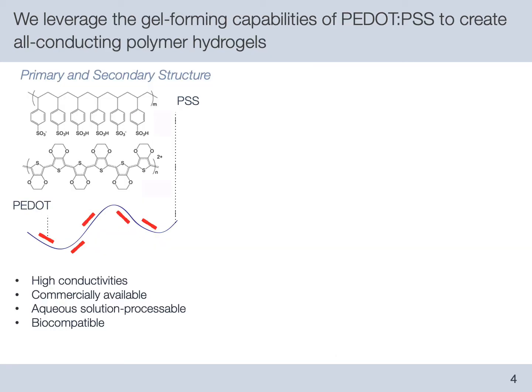To accomplish this, we leveraged the ability for a conducting polymer called PEDOT:PSS to form hydrogels from very dilute solutions of polymer and water. PEDOT:PSS is a two-component complex where PEDOT can conduct charge across its conjugated backbone, and PSS acts both as a dopant and a way to disperse the insoluble PEDOT in water. It is commercially available as an aqueous dispersion of 1 to 2 weight% and has been frequently used in the form of solid films and coatings because of its high conductivities and its good biocompatibility.